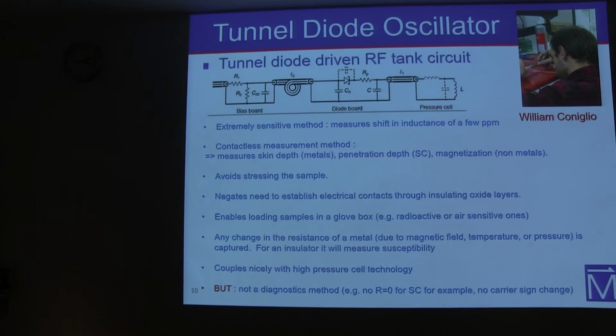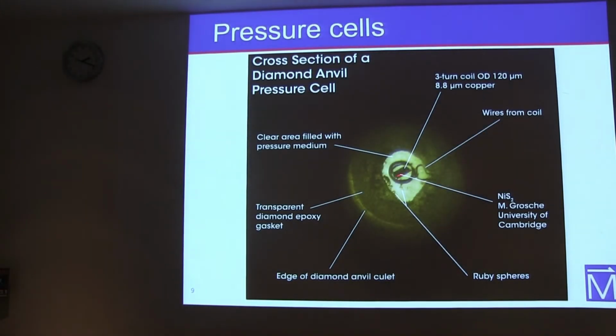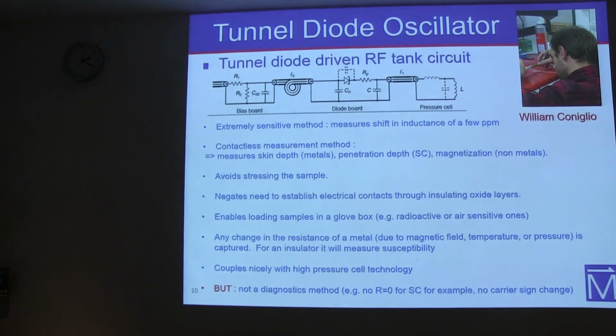Think about the dimensions of that sample. Here it's typically a 100 micron diameter sample, 20-30 microns thick. So try putting a good, low contact resistance contact on that small sample. For us it's a big advantage to not have a contact on the sample.